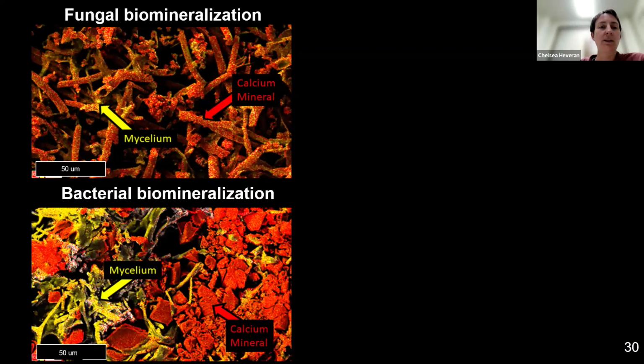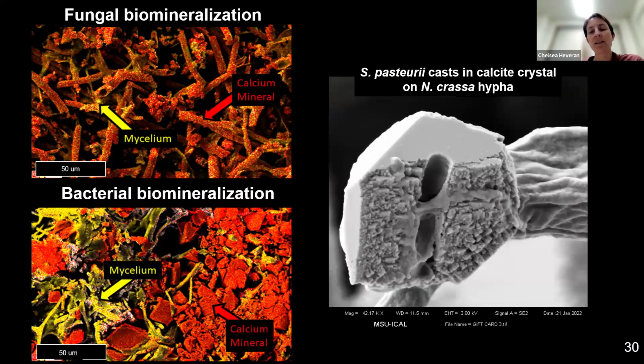Furthermore, when we look at what we built with fungal biomineralization, when it mineralizes itself, there's plenty of mineral, but it's mostly right on the fungal hyphae. When we mineralize it with bacteria, we get this beautiful, again, red here is the calcium-containing calcium carbonate mineral, this mineral that bridges together the scaffold, and that's what we want to see. I throw this image in for fun, but I think it's beautiful. What we have here is a fungal hyphal tip with a single crystal of calcium carbonate with bacterial casts on it, and it really shows you the spatial association between the microbes and what they're producing.